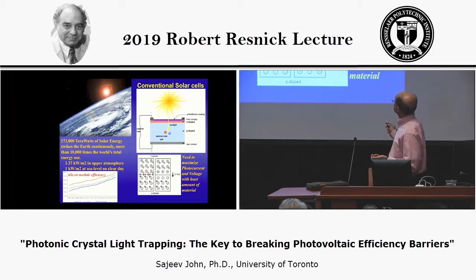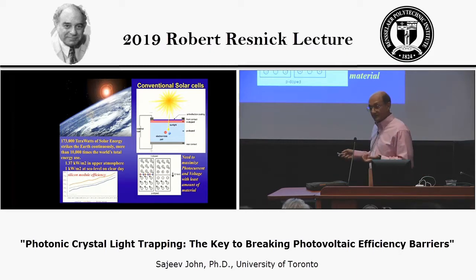So typically you have some doping, an N-type and a P-type region, where carriers from, say, one of these N-type regions can diffuse into the other region, leaving behind a net positive charge, and the result is an electric field that occurs across this junction. When carriers diffuse around inside of this bulk silicon region, when they come to the junction, they are separated in charge, and as well, the minority carrier, in this case the hole, the positive charge, has a very difficult time re-entering this region so as to recombine and to dissipate the energy. So this is the strategy behind what goes into a solar cell.